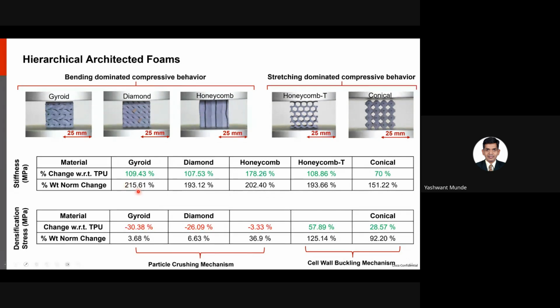So we see that because the walls of these architectures are now stiffer, it manifests as an increase in stiffness, and the weight normalized increase is even higher. When we compare densification stresses, the bending dominated ones showed a drop in the densification stress, whereas the stretching dominated ones showed an improvement. This is primarily because of the change in mode of crushing. In this one, it is just the particle crushing mechanism, and because the larger particles crush easily, we saw a reduction.